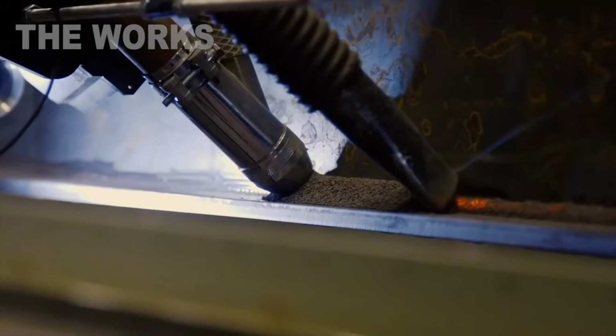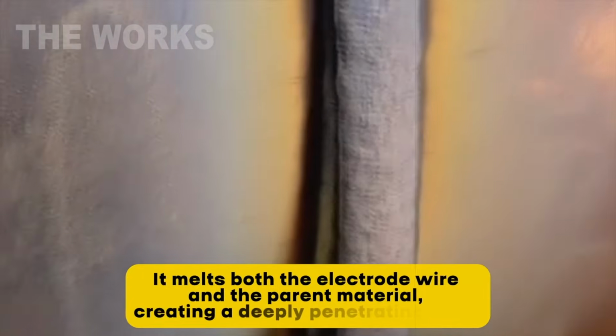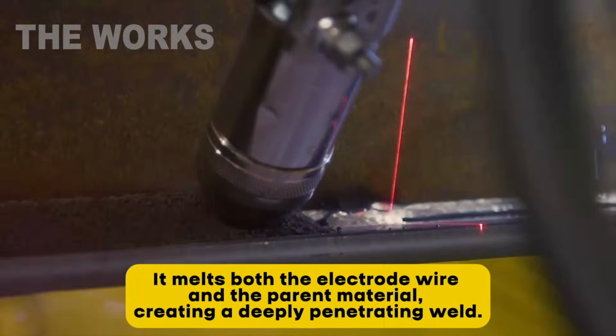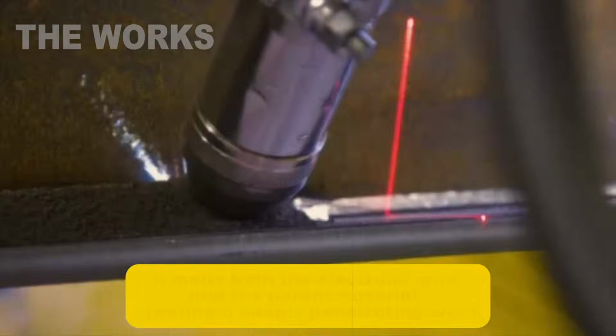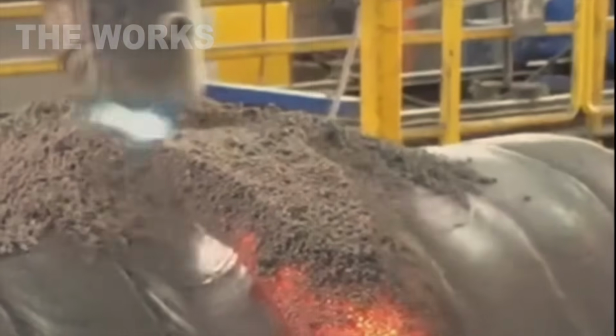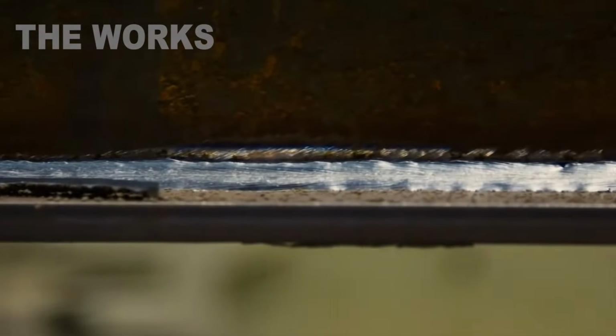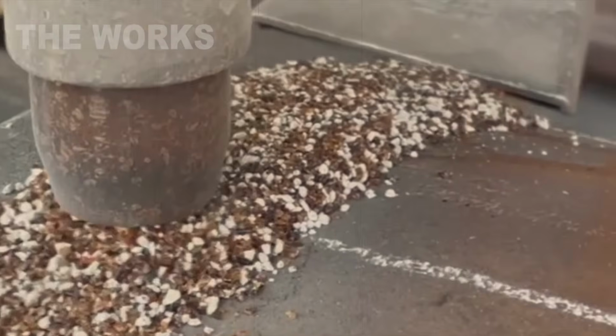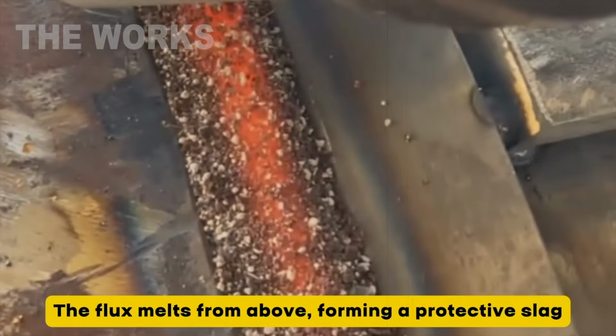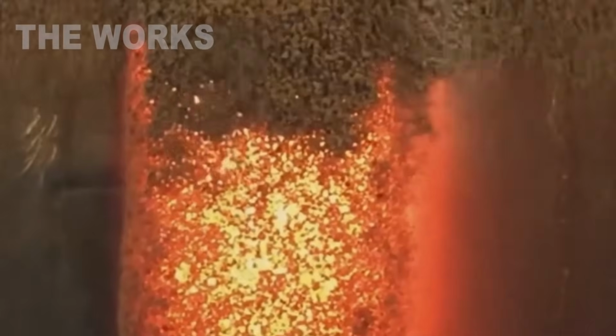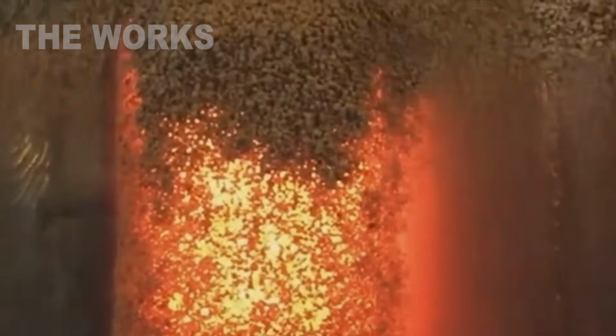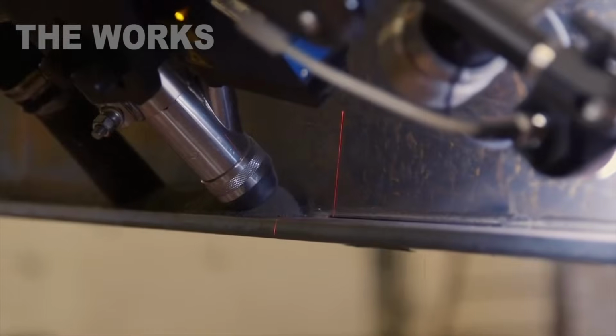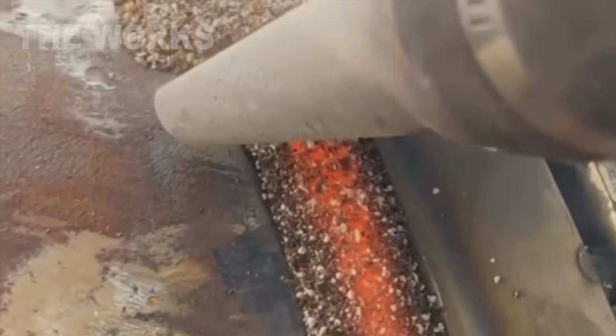But you can't see any of this happening because it's all taking place under that protective layer of flux. The flux melts on top, forming a protective slag that operators chip off later. Watch the welding head move along the joint. It's typically automated for consistency. The process can deposit weld metal at rates that would make a stick welder cry with envy, 10 to 50 pounds per hour depending on the setup.